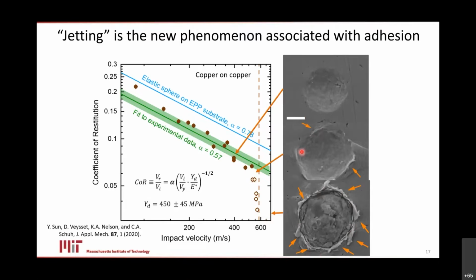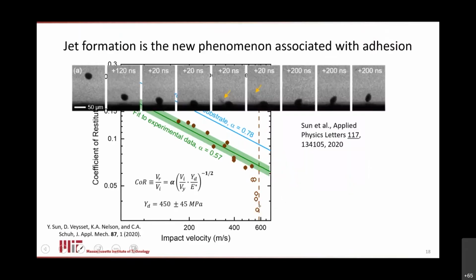So here is a crater. So this particle bounced, but it also left behind jets all around the edge. So indeed, we have evidence now that it is this phenomenon, this jetting at the edges, that is really what's going on in this divergent regime.